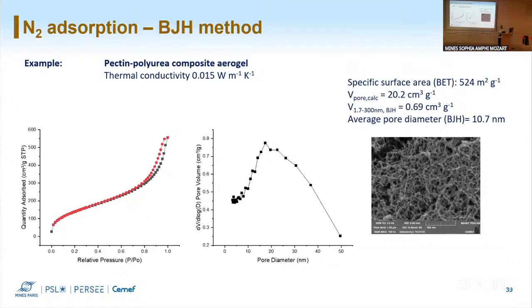What I'm trying to say is that we know we have a certain volume of pores, and when we do the nitrogen adsorption measurement, the BJH method, which was supposed to give us the pore size distribution, considers only 3% of our pores. After discussing, we say that since this model does not consider our pore volume as a whole or a big fraction of it, we cannot say that we have an average pore size of 20 nanometers, because this would correspond to 3% of our volume. Yeah, there's definitely something strange. I agree with you.